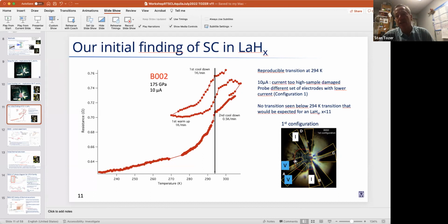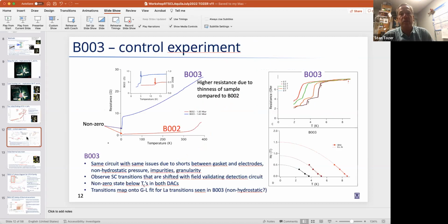This configuration has current across these two electrodes, with voltage being measured here. So in this region, we see this very interesting material, and it's also at 10 microamps. We were concerned that we were going to damage the sample, so we switched and went down to 600 nanoamps and also changed configurations so we could look at two permutations.